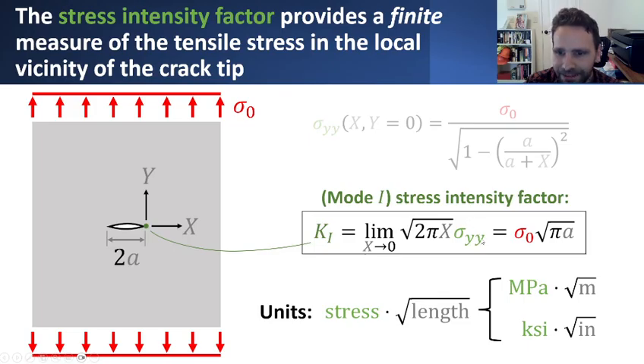So really this expression, the mode 1 stress intensity factor, being defined through this limiting function, given some exact solution for what the sigma yy stress field should be in this particular problem, in the limit as you approach the edge of the crack, is the proper definition of the stress intensity factor. It requires that you solve the original elasticity problem for the stress field and figure out what its value should be when multiplied by this extra term in the limit as you approach the actual location of the crack tip.